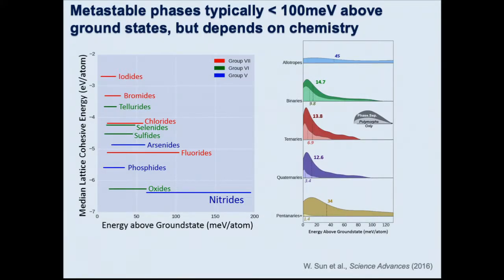Okay, if you look at this across chemistries, and this is definitely not a complete list, this is the typical energy above the ground state of metastable compounds. And this is the 10th and the 90th percentile. And what you see is a lot of them are very similar. They reach up to about 100 millielectron volts per atom. If you're a chemist, that's about 10 kilojoules per mole. I can't do British thermal units, or kilocalories. But of course, then you see nitrides, for example, have much larger metastability, right?